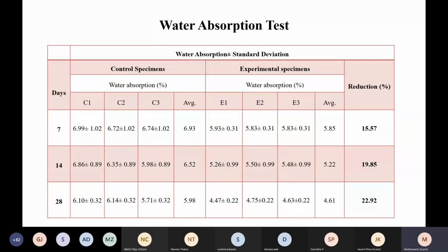Coming to water absorption test. As you can see, the reduction in water absorption, percent reduction, 15.57 in experimental as compared to control on the 7th day. Percent reduction of water absorption of experimental cubes, that is biocemented cubes, was 19.85% on 14th day as against control cubes, and percent reduction of water absorption of experimental cubes was 22.92% on the 28th day as against control cubes.